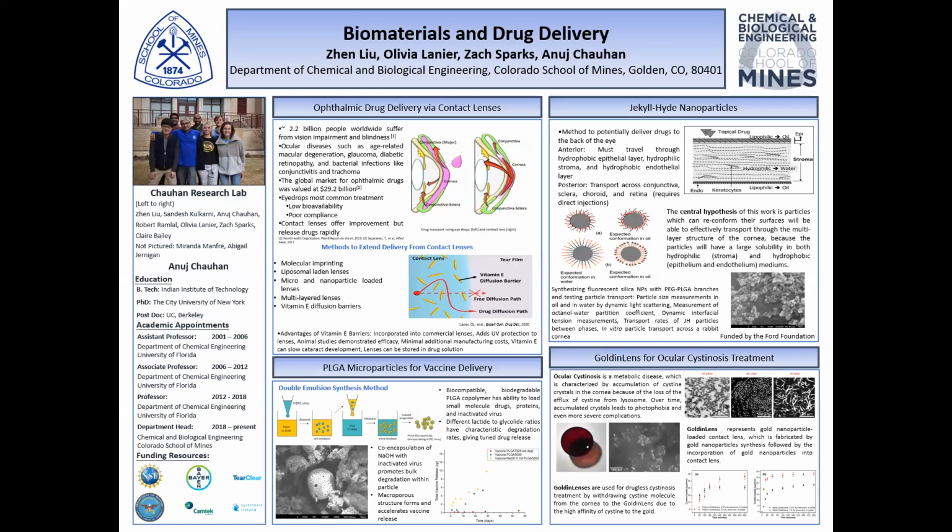This is a challenge as the cornea possesses hydrophobic and hydrophilic layers. In order to permeate the cornea, this will require the particles to be amphiphilic in nature. One of the particle syntheses that has been tried is a silica core conjugated with streptavidin in a biotinylated PLGA-PEG polymer chain. By adding the biotinylated PLGA-PEG chain to the streptavidin-conjugated particle, we're able to bind the polymer chain to the silica nanoparticle.